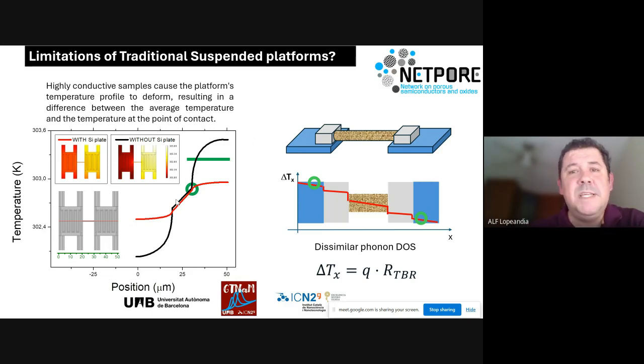And there is a second intrinsic problem. This one can be, how to say, slightly softened if we introduce a highly conductive material underneath the platforms in order to homogenize, to increase the heat diffusion within the platforms. And this is with a 100 nanometer monocrystalline silicon plate under the platform, where we can more or less reduce that effect, the temperature drop. This is the temperature scale. The temperature drop and the average temperature in the red line in the platform is more or less the same as the one we got at the point. It's not exactly the same, but it could be more or less considered so, because the error will be smaller.